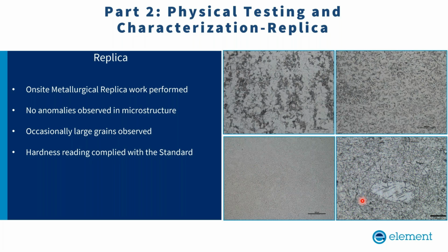An on-site hardness test was conducted, and it appears that the hardness value was as per the relevant standard, which further confirmed the integrity of the material. So in summary, the on-site replica and hardness tests suggested that the material of this asset is in good condition. There was no sign of significant deterioration or degradation of the material during the operational life of the asset.